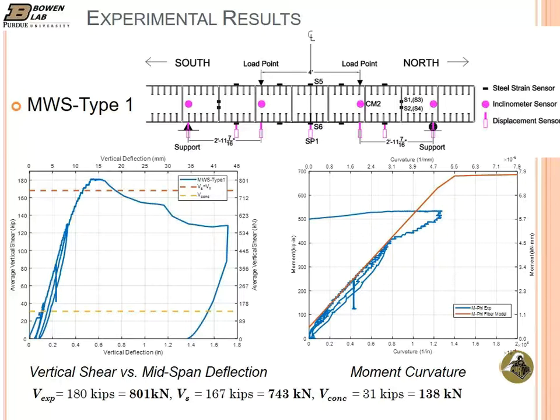In this plot, we're looking at the moment curvature response, and we obtained the curvature through the rotations that we measured under the load point. Since we have a constant moment region in between the load points, we can assume constant curvature in that region, estimating the curvature by dividing the rotation by the distance in between the sensors. That's how we obtain the curvature, and then the maximum midspan moment is plotted on the y-axis. We also compared this with our 2D fiber model. We did a basic section analysis, assuming full strain compatibility between steel and concrete, no slip in between layers. When we compare, that's the red line there, and it's almost a perfect match. So we had full composite action for this beam.